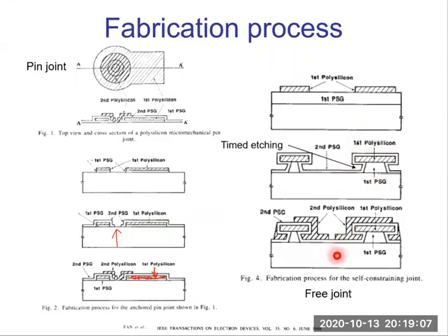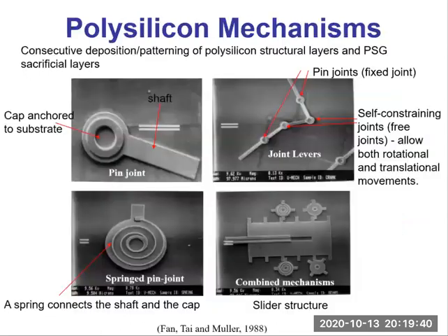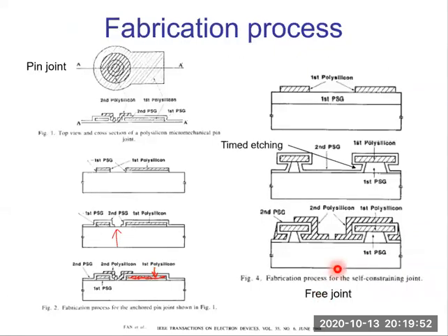Then deposit and pattern the second polysilicon layer. This is the second polysilicon layer. So this will form the cap structure. But this cap is not anchored to the substrate. You can see it's not anchored to the substrate. So after sacrificial etching, the shaft, again, the shaft is a first polysilicon layer, can have both rotational and translational movement. That is because the second polysilicon layer is not anchored to a substrate, so it allows both rotational and translational movement after sacrificial etching.